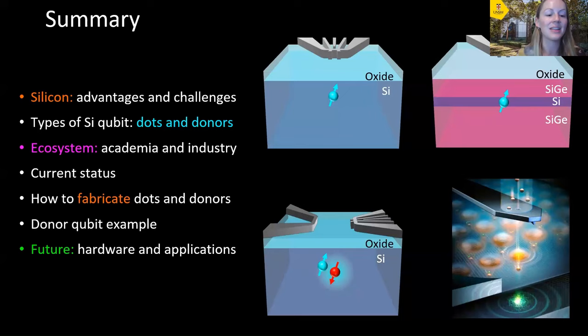And then when we look at the other option, which is the work done by Professor Andrea Morello and my team at UNSW in collaboration with the University of Melbourne, we've got the ion implantation method, where you basically just fire an atomic gun, you shoot your ion into your silicon, and it comes to rest. And so you don't have the atomic placement precision. In fact, it's more on the order of, say, 5 nanometers or so that you can roughly aim to get your atom to live. And this means we don't have very precise choice over our couplings if we go to the small length scales with, say, exchange coupled donors. But if we move to this clever flip-flop qubit architecture, it gives us more flexibility with where we're placing our donors, because we're using this longer scale electric dipole coupling mechanism. And another nice bonus of the ion implantation method that I find really interesting is you can implant different species of donors. So not just the phosphorus, you can also have the higher spins with the antimony, and gives you more exciting things to do with more energy levels and potentially makes it a more scalable system. So yeah, hopefully that answers your question.